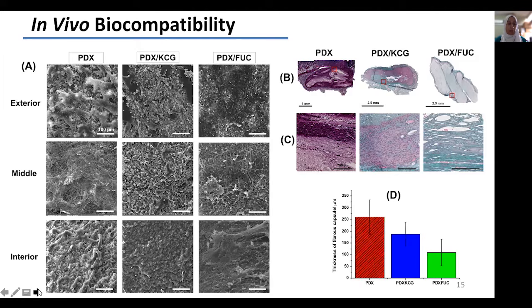We also took out a piece of the tissue at the subcutaneous pocket site, and we analyzed it in terms of histological analysis. And the image on the upper right-hand side shows that for all the 3 scaffolds, we had the presence of a fibrous capsule that was formed around the scaffolds. But if we look closer, the thickness of the fibrous capsule varied depending on the nature of the scaffold. Therefore, if we look at the graph on the lower right-hand side, we can see that the fucoidan-containing scaffold led to the thinner fibrous capsule in comparison to the kappa-carrageenan-containing scaffold or the pure PDX-containing scaffold. Therefore, overall, we can say that the incorporation of fucoidan leads to better in vitro and in vivo cellular response compared to kappa-carrageenan.